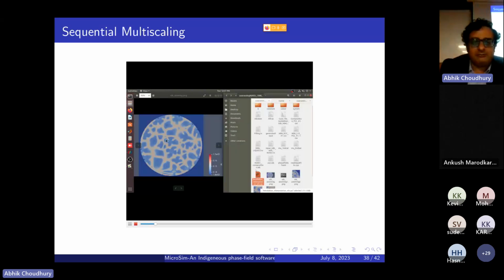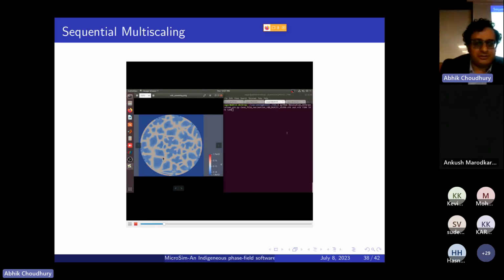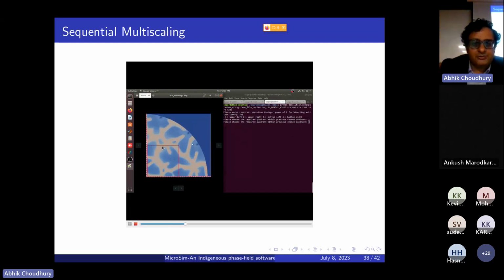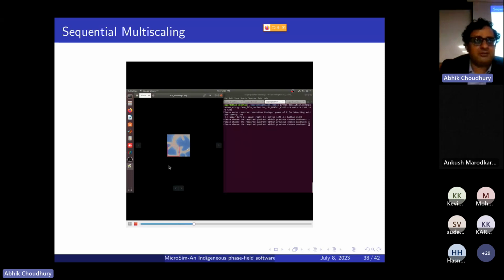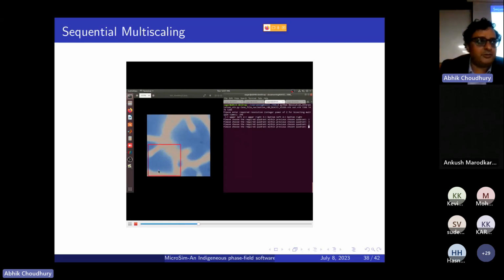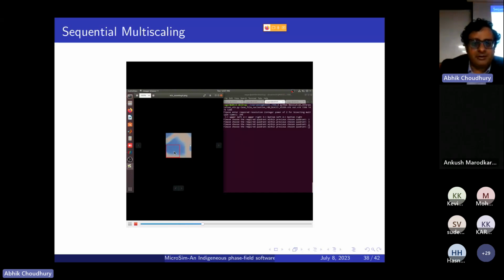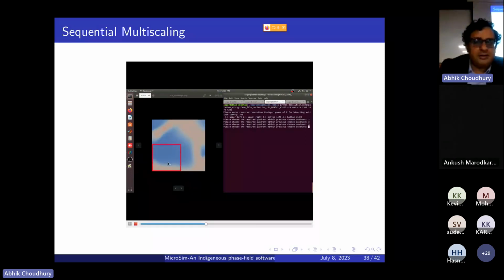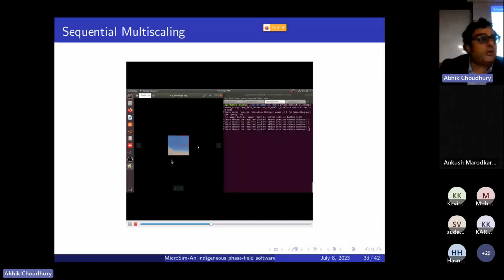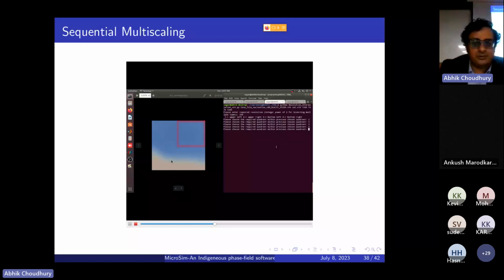So let's say this is a microstructure that is derived out of the solidification of a droplet, where you have dendritic microstructure in a droplet. This is something that is relevant for atomization problems, where you have solidification evolving. But now I want to extract a little bit of this microstructure. We have a tool over here called resolution interpolation (VTK), and what it does is break up the domain into smaller parts, and you can keep recursively choosing smaller and smaller parts of the domain until you reach the desired position in the domain that you want to simulate further. So here we are going recursively into smaller and smaller parts of the domain, and taking out the composition fields that will be relevant for the post-processing that you would like to conduct.